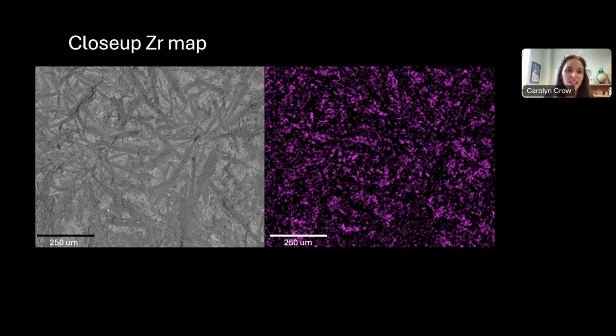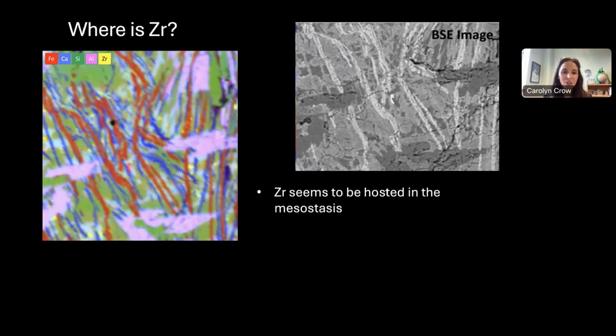So here's a close-up zoom in. On the left is the SEM BSE image. Sorry, it's not labeled. And over here on the right is a zoom in zirconium map. What you're maybe starting to see is that there's zirconium everywhere in the sample, but there is nothing bright sticking out associated with that in the BSE image. So we saw this, we started to get a little disappointed, and we said, okay, we're going to do some even more in-depth mapping. And so here we zoomed in even further to figure out where the zirconium is.